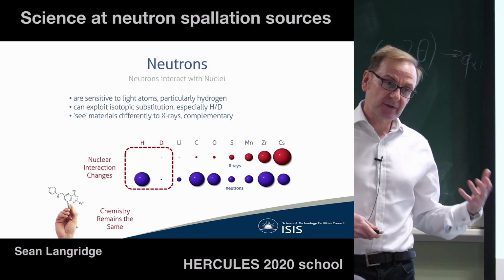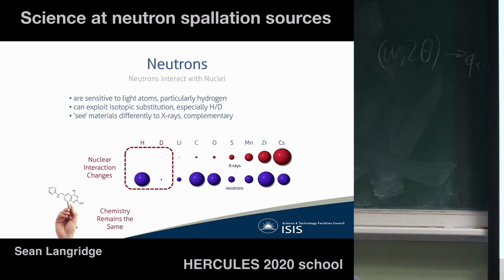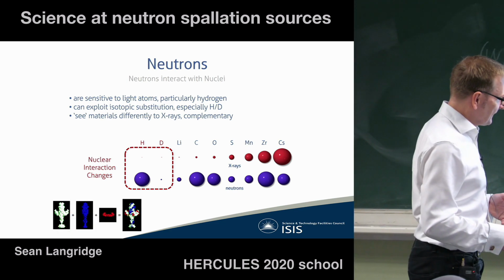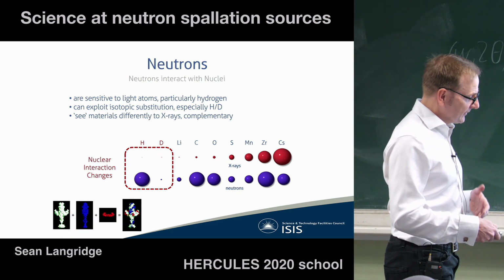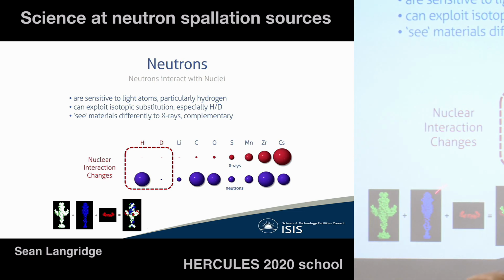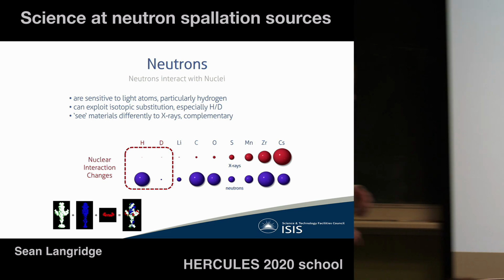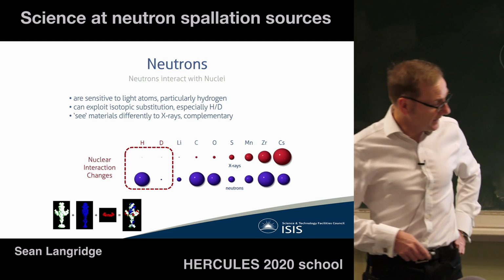So the different parts of the sample will scatter differently depending on whether they have hydrogen or deuterium, and this allows us to do, this is a case of low to medium resolution small angle scattering, where one takes the atomic structure from X-rays of this particular system, deuterate different parts of the molecule, and you can get a really accurate description of a material in solution that you couldn't do with any other technique.